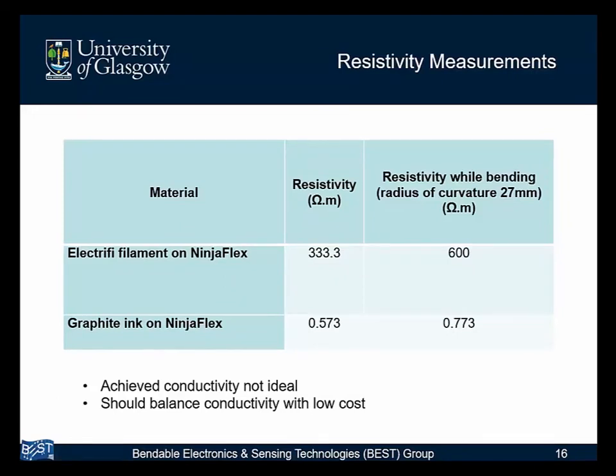For some resistivity measurements, to get an idea of the resistivity of these materials, the electrifi filament, as we found, showed a much higher resistivity than commercially stated, or even stated in another piece of research. So this was quite alarming to us, because we wanted a repeatable process. But it also maybe opens our eyes, and the eyes of the field, in terms of producing filaments that can suit a variety of different printers, but also in terms of the properties of printing itself, for example, the printing temperature or the printing speed, etc.